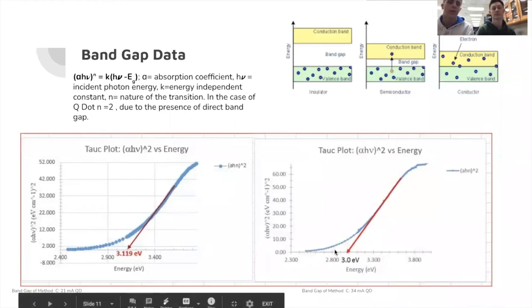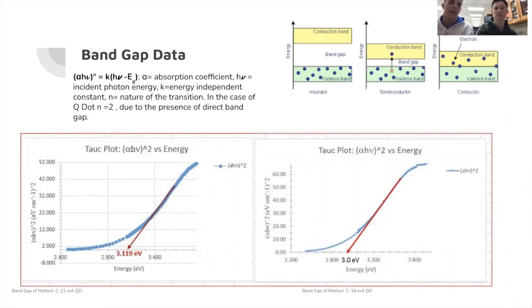Along with that, we got our band gap energy from the solution. We took the Tauc-Davis-Mott equation and we got our results and made a Tauc plot, which we did alpha h nu squared versus energy. We took the tangent line of this plot, and where that tangent line hit the x-axis we found our band gap in electron volts, and that was around 3 to 3.1 electron volts.